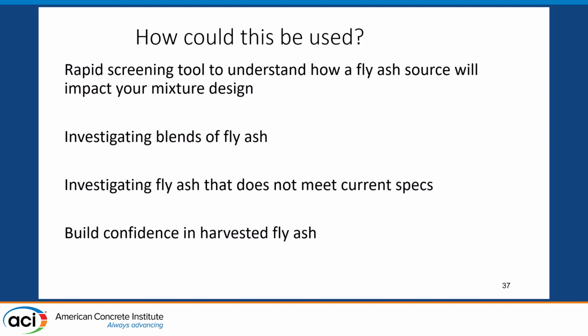You can look at blends of fly ash. So you have an on-spec fly ash and an off-spec fly ash. You have a C and you have an F. You have whatever, okay? Because of fly ash shortages, people have been using C's and F's in one concrete mixture. That wouldn't be something you would usually do, but they're doing it now. You can see how the blends perform. You can investigate fly ash that doesn't meet current specifications.